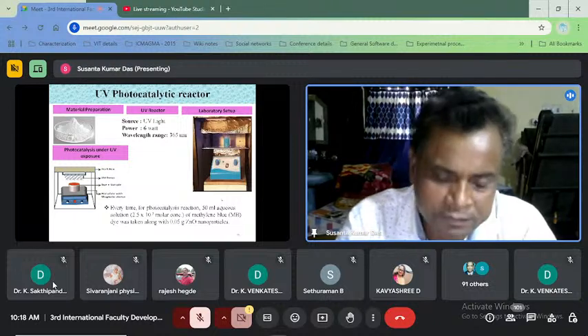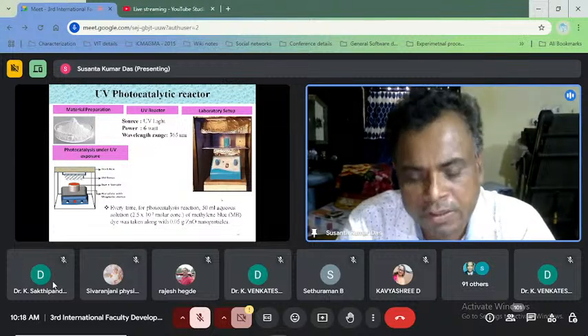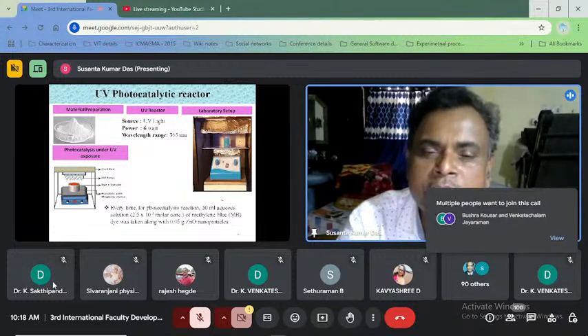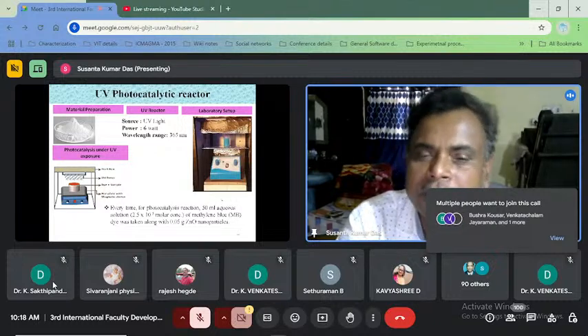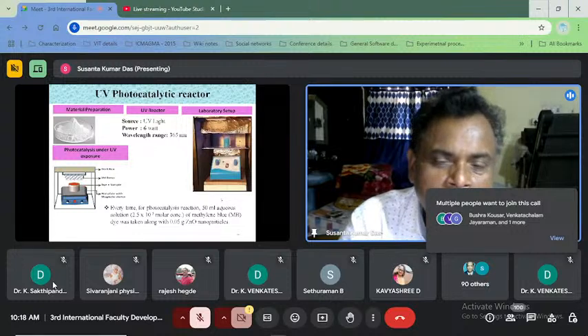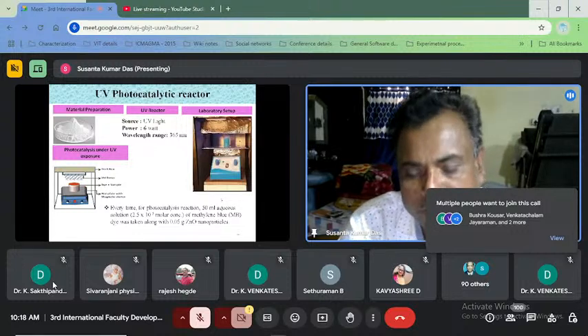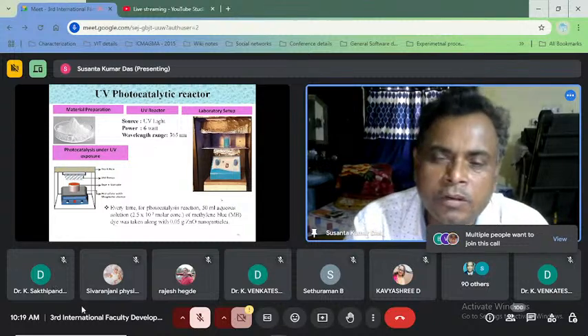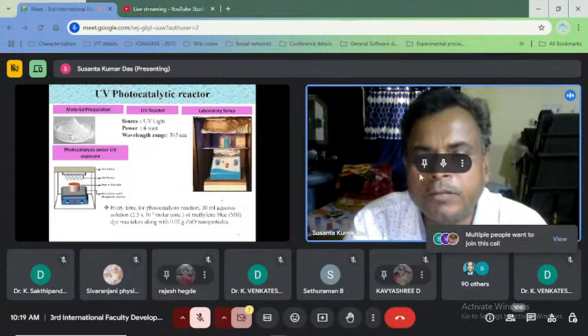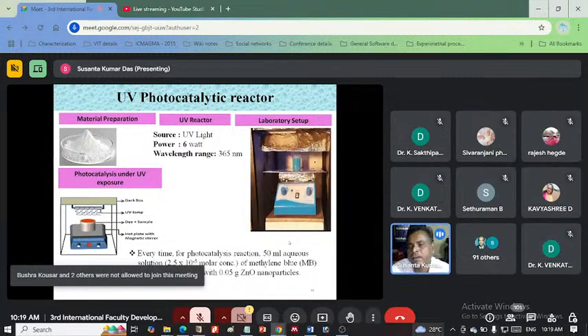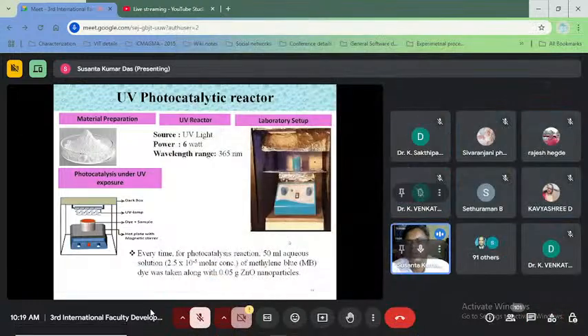That was a private, and still is a private university. It's now a very big university, having 25,000 student capacity. But at that time it was a small university, and we started these things almost from our own pockets. So at very low cost, I developed the reactor. It consists of a magnetic stirrer and a UV light source of 6 watt, with a wavelength of 365 nanometer. I tried different distance configurations, and I found that at this power level, 10 centimeter was optimum.